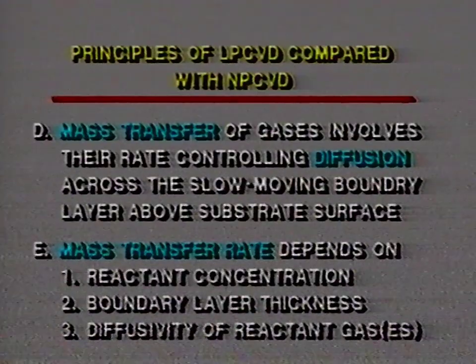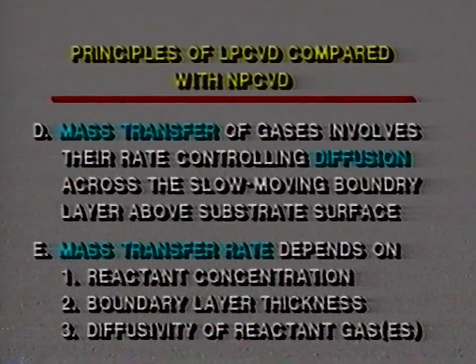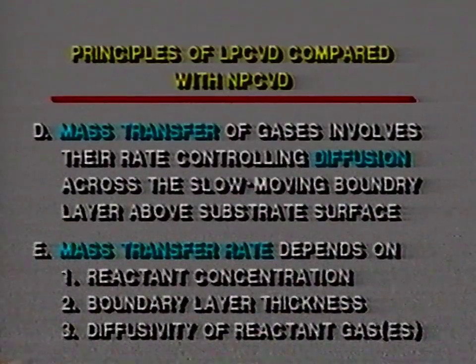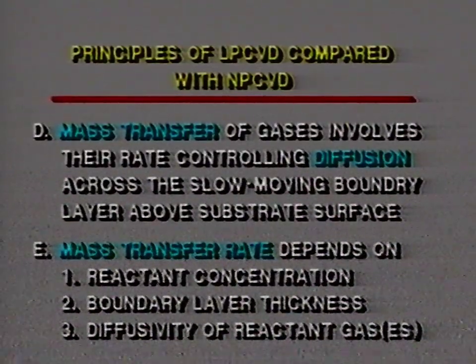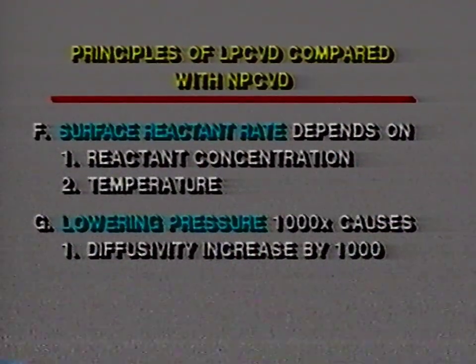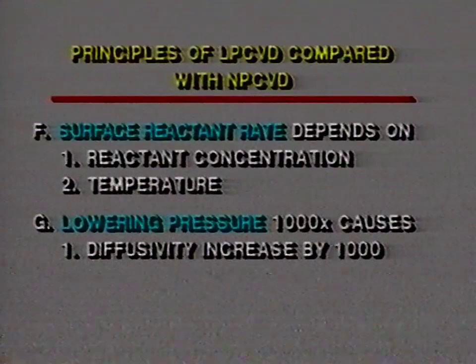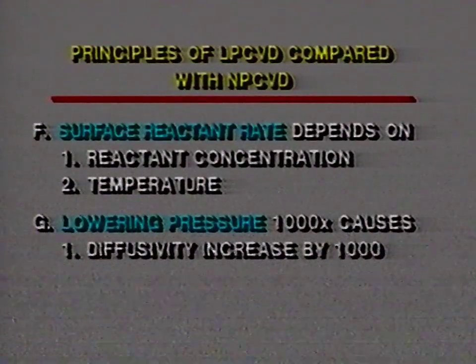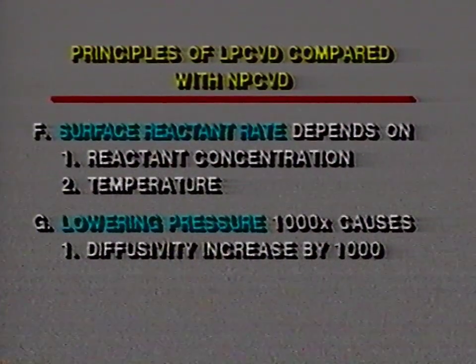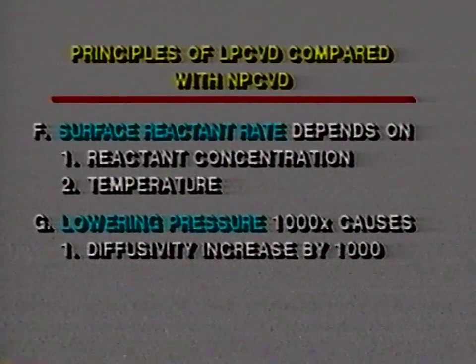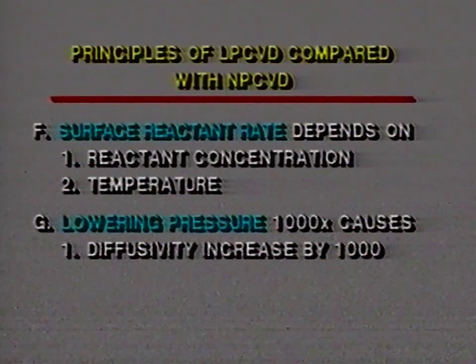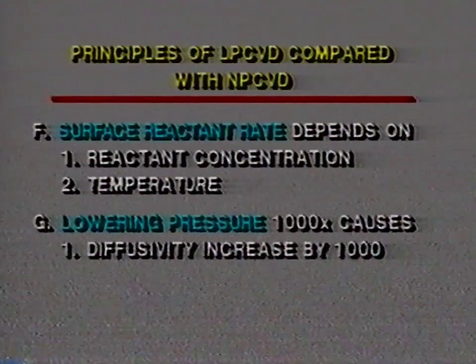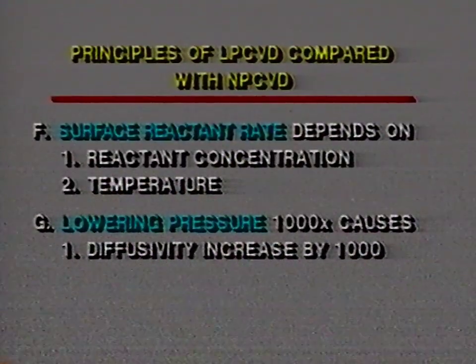Under E, the mass transfer rate now depends on a number of things, namely the reactant concentration, the boundary layer thickness, and the diffusivity of the reactant gas or gas mixture through that layer. And the surface reaction rate, on the other hand, depends on the reactant concentration and the temperature only.